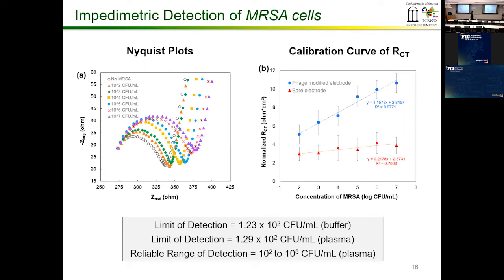So you can see a similar set of experiments and the calibration curves. When you don't have the bacteriophage present, the change in the impedance is not high, but when you have the phage present, you can see there's a significant increase in the impedance, meaning that the electrode is attracting bacteria to the surface, and it's able to detect with a much higher sensitivity. The slope of this curve would give you the sensitivity, and of course the intercept would give you the limit of detection. So the limit of detection in this case has gone down by 1 order of magnitude. Now we're at about 100 cells per ml.